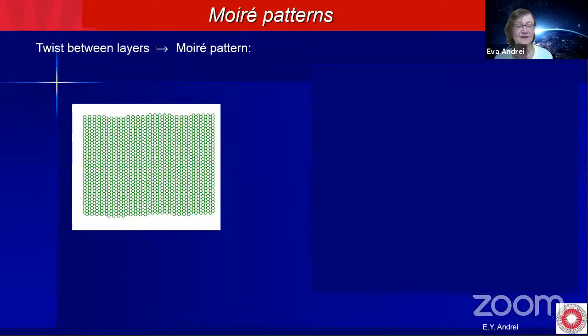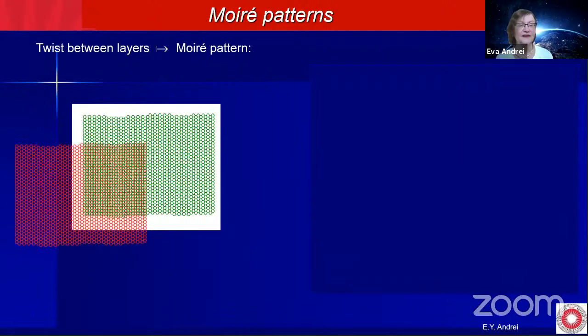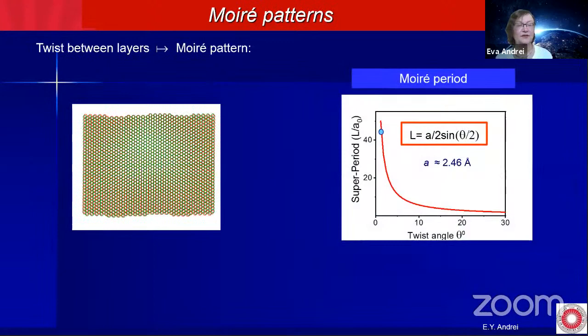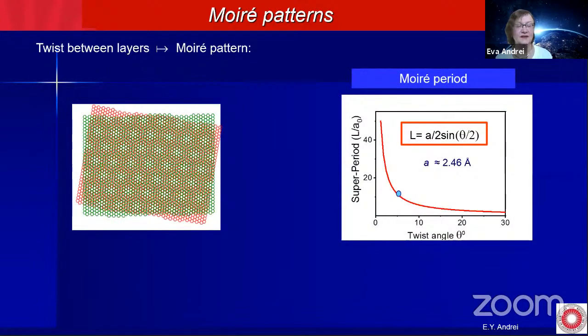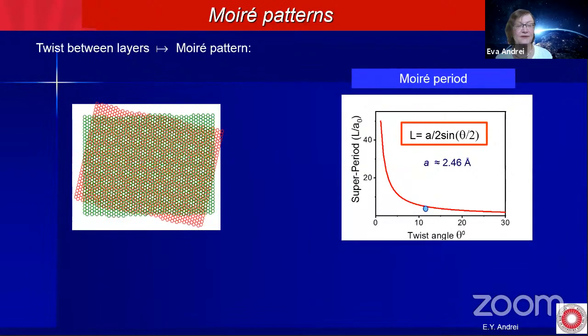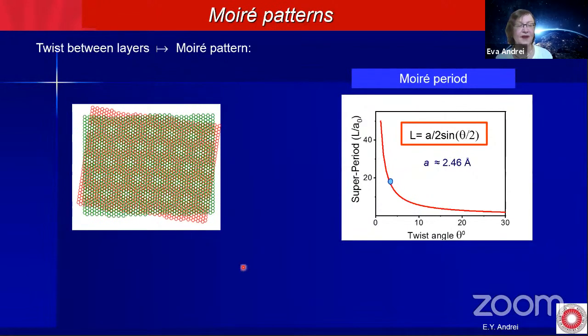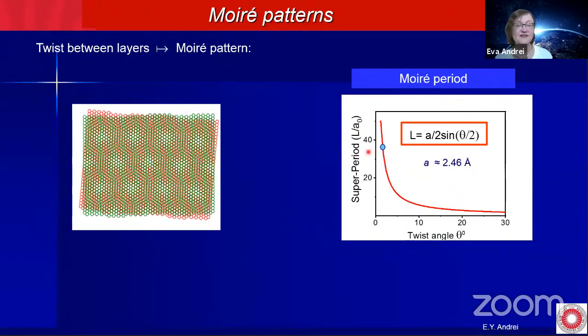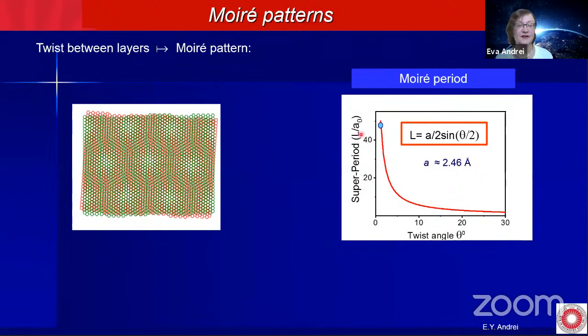So let me show you what happens when you superpose two layers. Here we have the first layer of graphene. I'm going to bring another one on top and twist it. So what happens, you create this super pattern here, which we call a Moiré pattern. And the smaller the twist angle is, the larger the period, the super period of the pattern. You see the pattern period is inversely proportional to the twist angle here.